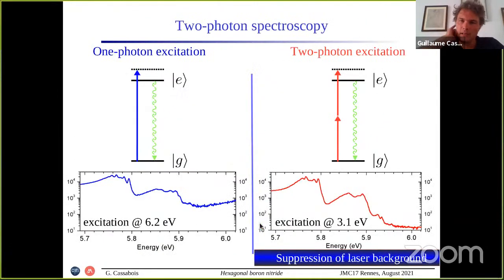The way we could study this in Montpellier a few years ago was to perform two-photon spectroscopy in hexagonal boron nitride. I am plotting on the left side the one-photon excitation: we excite HBN at a wavelength around 196 nanometers, above the bandgap. We generate carriers above the bandgap, these carriers relax, and then we have the emission of one photon. Here I am plotting the emission spectrum of HBN in the deep ultraviolet on a semi-log scale, really zooming in on the emission close to the band edge.